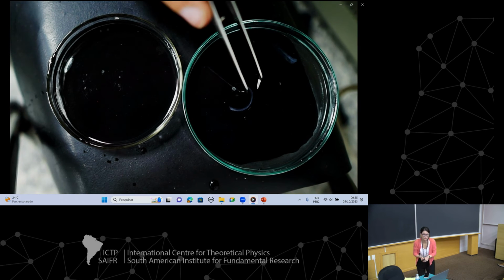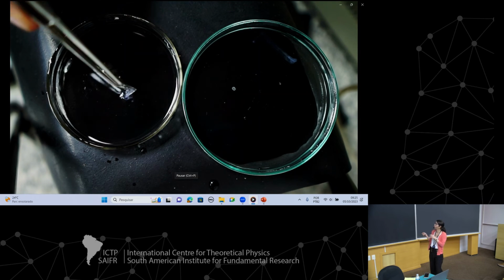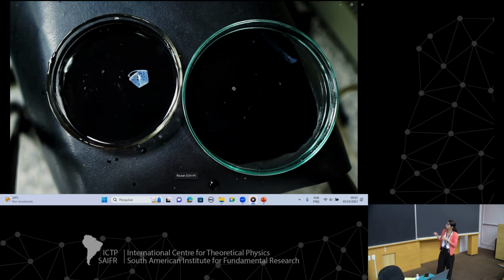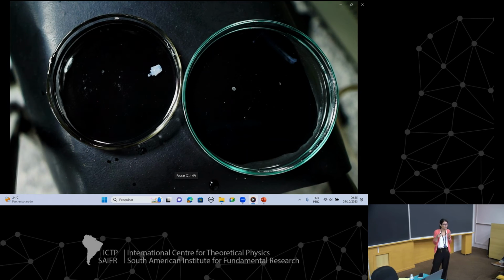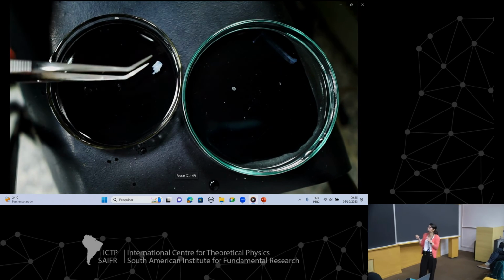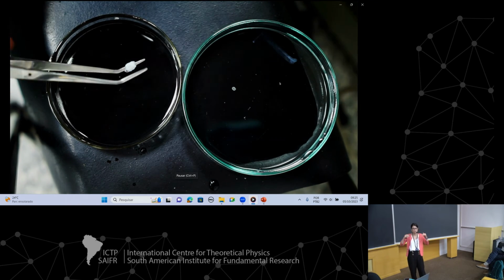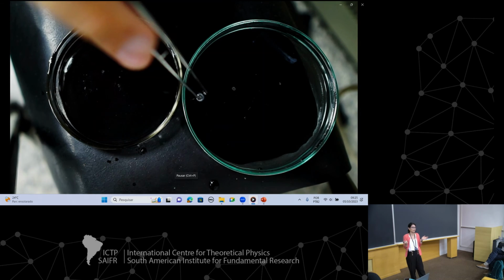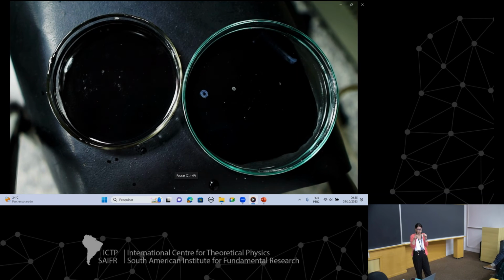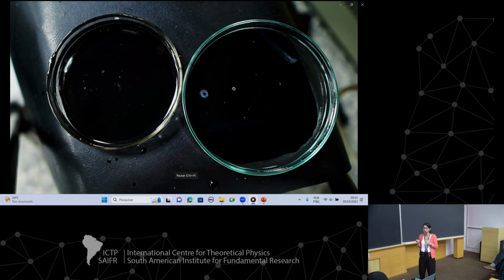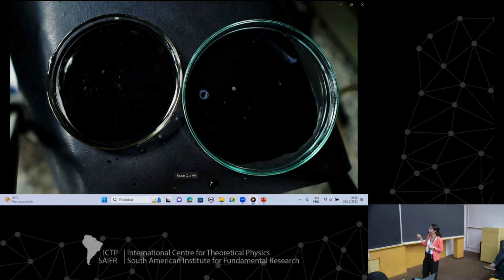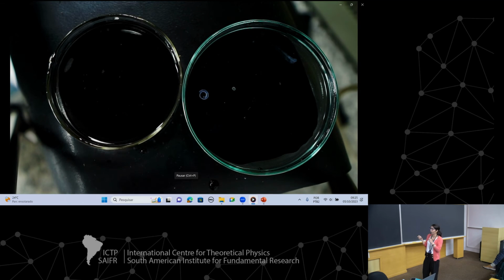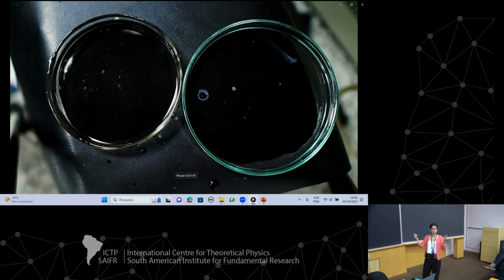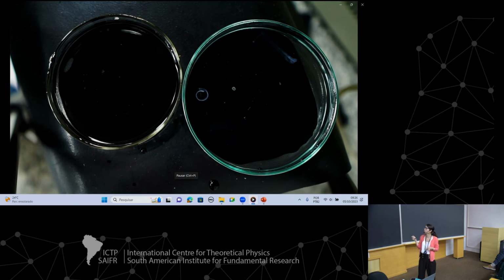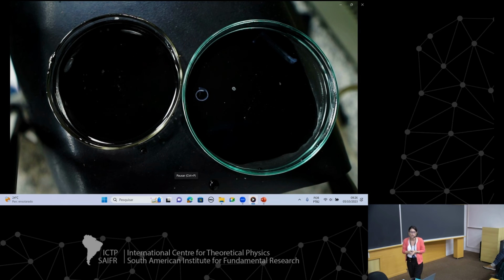So here is a filament at high pH. Placing it in low pH, it shrinks. No, sorry, in high pH, the outer part swells, so it entails the buckling of this filament, and coming back to low pH, it opens again. It takes a little bit of time, so this can be a problem for application, but we checked the shape morphing.